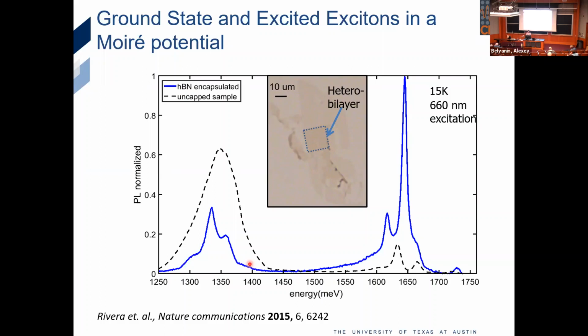Now instead of 2 layers, you need 4 layers. Hexagonal boron nitride, they're different phases: the cubic boron nitride, hexagonal boron nitride. Interestingly, for people interested in material science, everybody gets these crystals from a Japanese group. To perfect the growth, they grew it 900 times. So if you're frustrated as a graduate student because your experiment is not working, just know it doesn't work at the beginning for everybody. But these groups are now the sole supplier for all groups around the world working with these materials. So when you encapsulate them, the uniformity of the Moiré superlattice gets better.